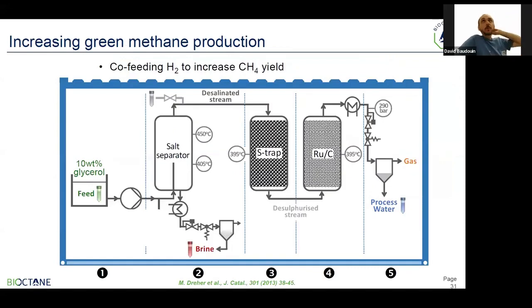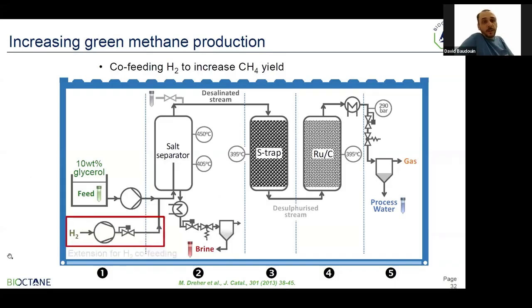One aspect you have seen earlier is that methane is produced in large amounts, but also CO2 alongside. One approach that can be followed is to co-feed hydrogen with wet biomass into the process. Next slide, please. This was done in the group. At the moment, we have only done it with a model feedstock, glycerol in this case, and together with glycerol, hydrogen was pumped in along the feed at high pressure.